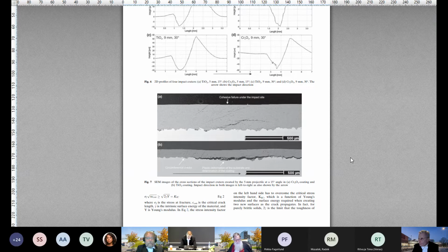Well, that would be, especially knowing now what I know of this test, the idea of adding the ceramic coating would not be to increase the ballistic protection of the steel. So we wouldn't be considering the properties of the substrate material that much. It's more in a characterization of the coating. Okay, thank you. So you're saying that benchmarking is not warranted in this case? At least with these materials, you would not want to protect or consider protecting a steel with the thermal spray ceramic coating against a bullet.